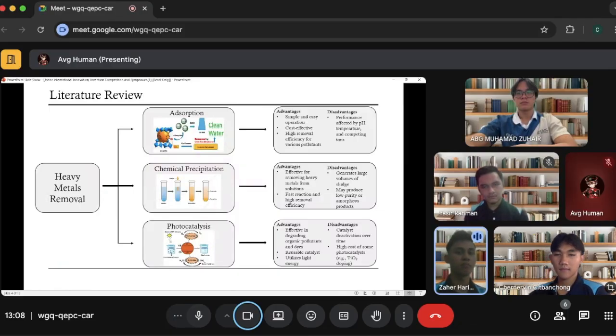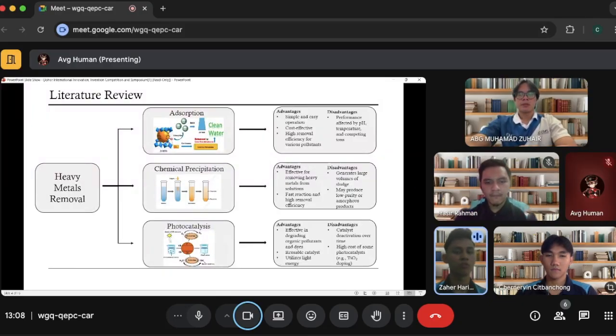We compared three approaches for removing heavy metals: adsorption, chemical precipitation, and photocatalysis. We chose adsorption because it is simple, low cost, and highly effective, especially at removing metal ions like copper(II) from aqueous solution. Other methods had limitations. Photocatalysis needs expensive materials, and chemical precipitation creates a large volume of sludge. Instead of conventional adsorbents, we use iron oxide nanoparticles synthesized via a green route, which brings us to the next slide.